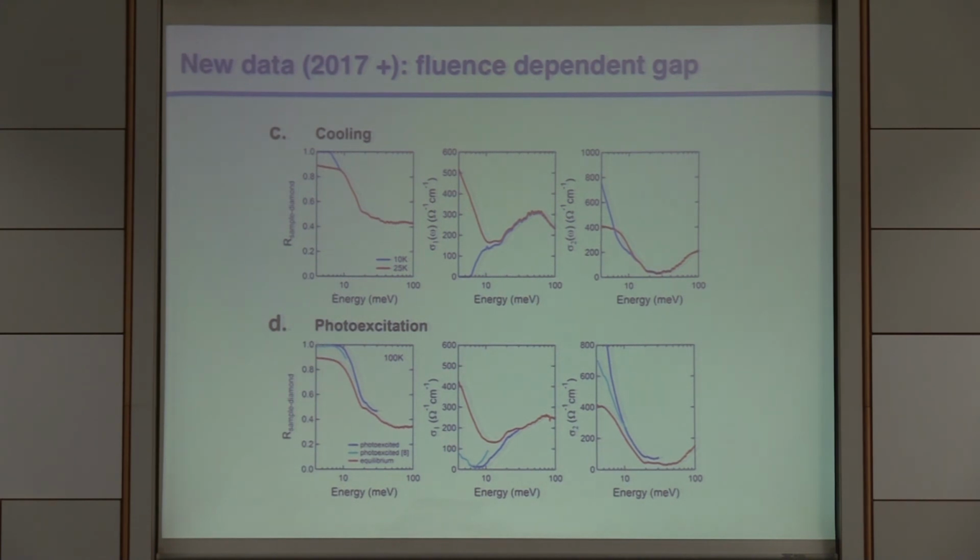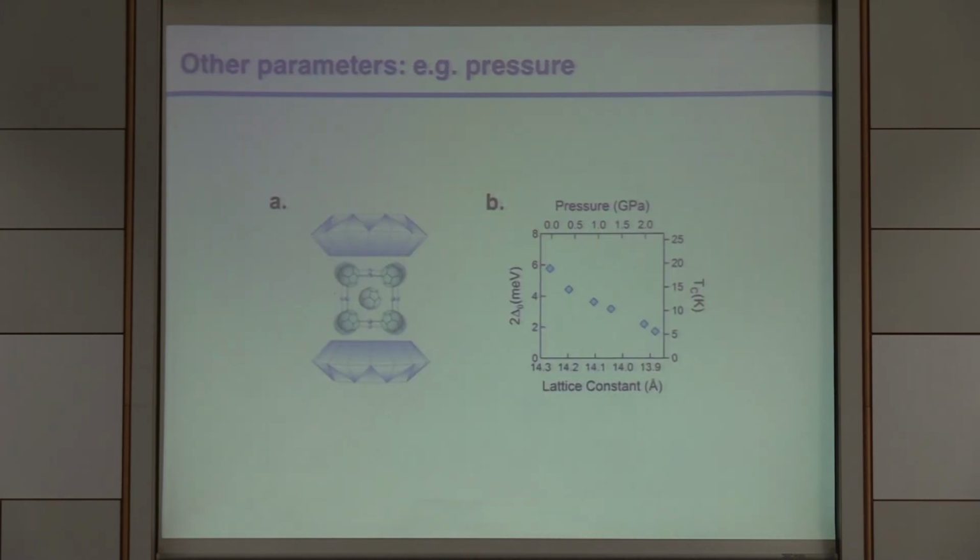The last thing that I want to show you is that, in principle, the presence of a gap and a divergent sigma 2 is compatible with a polaronic state with infinite conductivity, which has a gap and very high conductivity, but that is not a superconductor. So in principle, until you measure the Meissner effect, you cannot tell the difference in the optical spectrum between a high mobility metal, although the mobility would have to be incredibly high, and a superconductor.